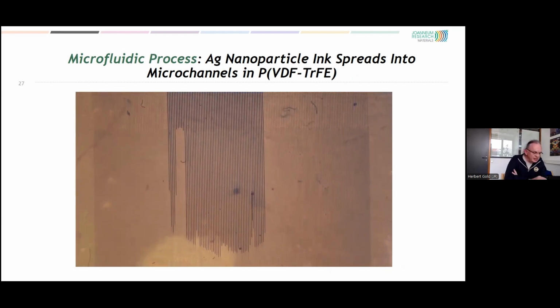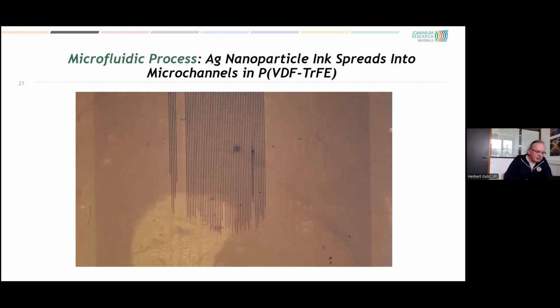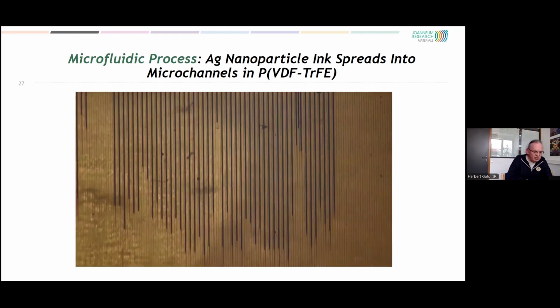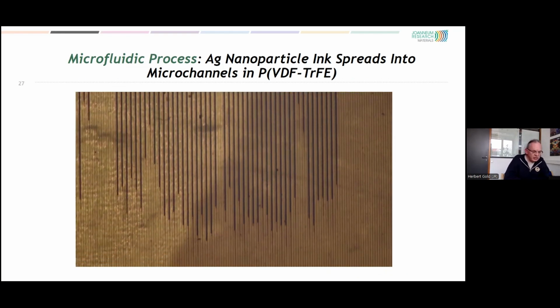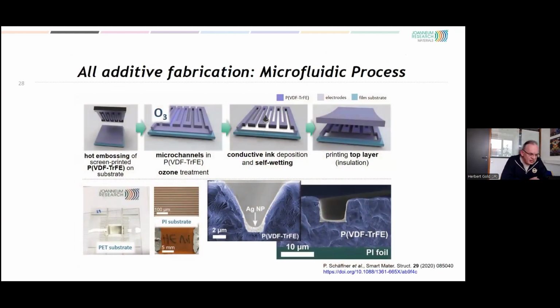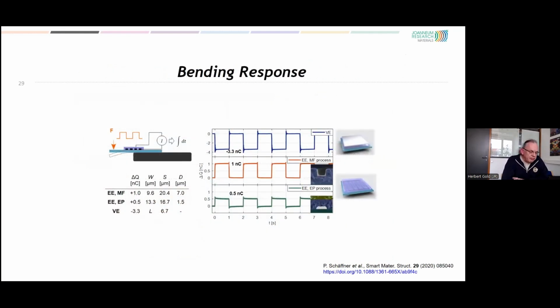We will not use exactly this process in the project, but we will also use nano-imprint lithography combined with other additive deposition methods. And so we arrive at this, on the bottom right, you see these channels. They are not really filled by the metal, but they are metallized. And this was sufficient that the sensor works equally well as the vertical electrode sensor. So here in the middle, you see that the sensitivity is reduced, but the quality of the signal is the same. So there is no erroneous detection or anything, right?